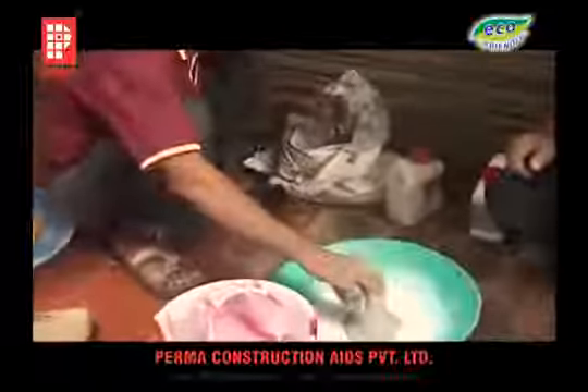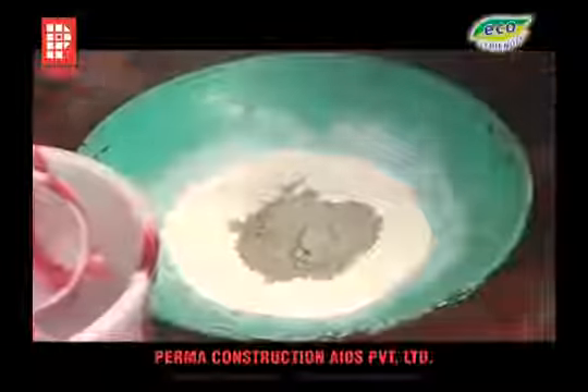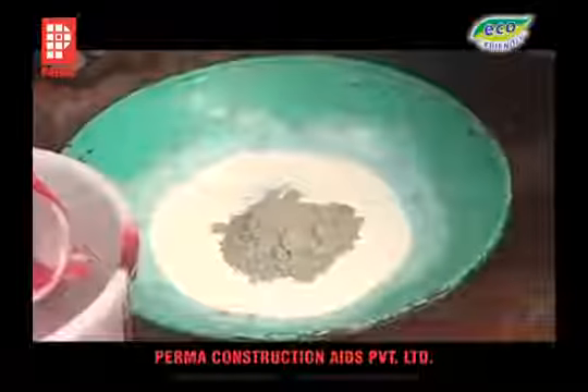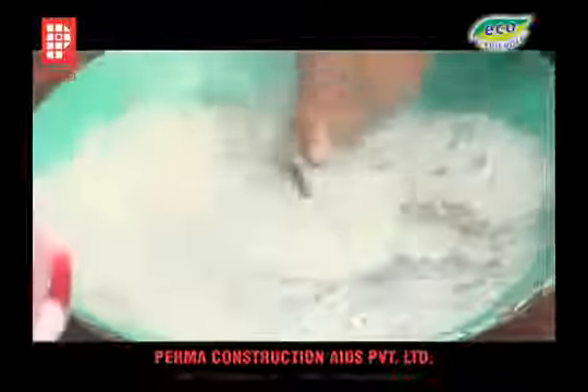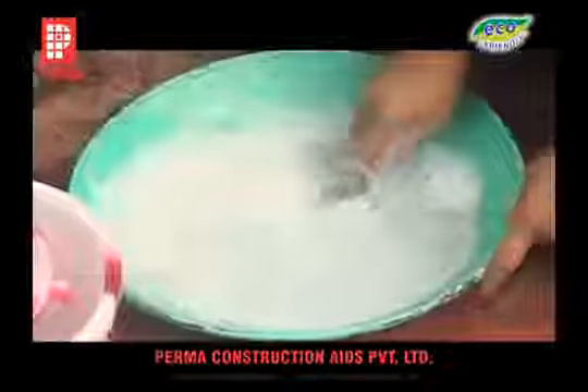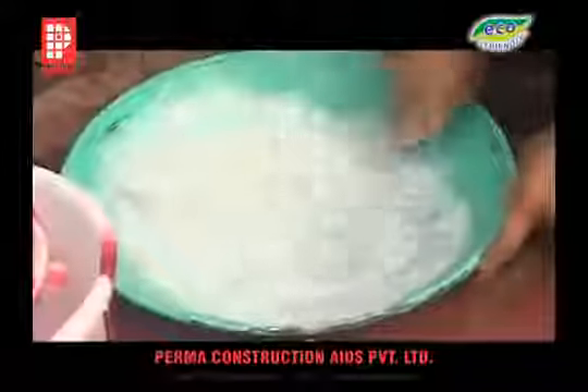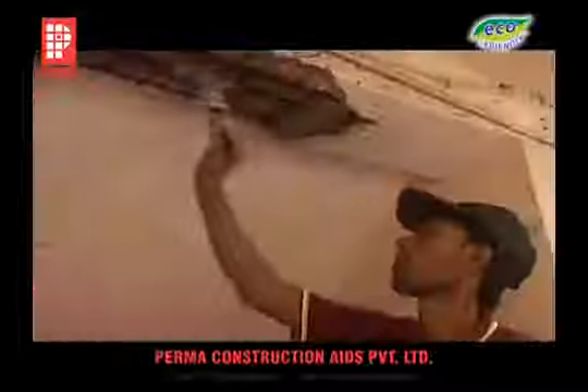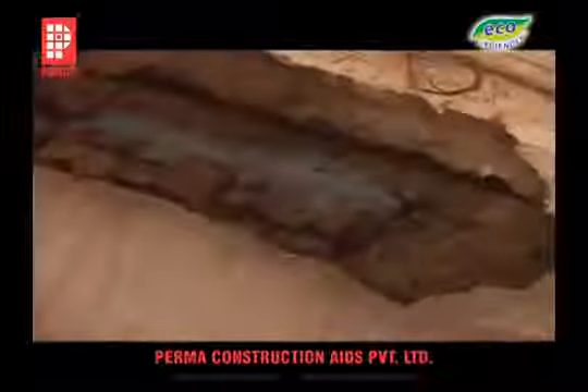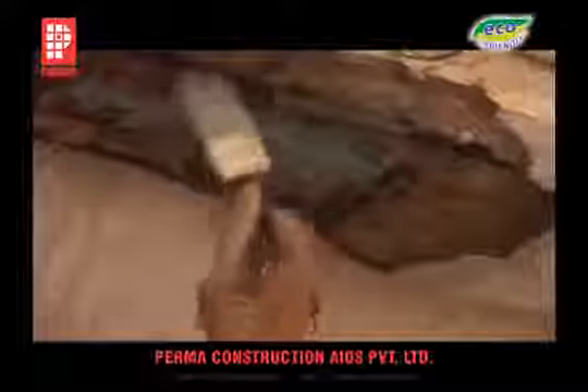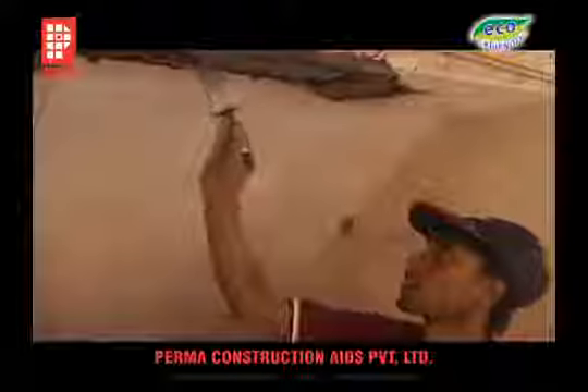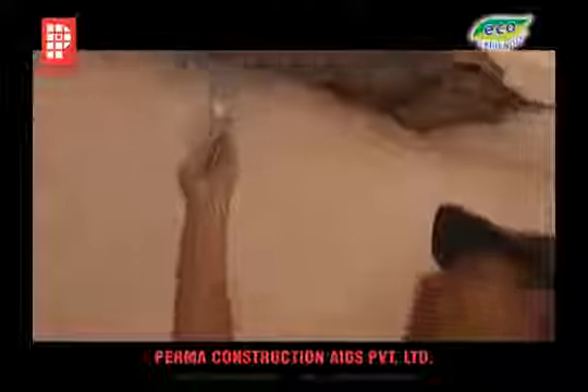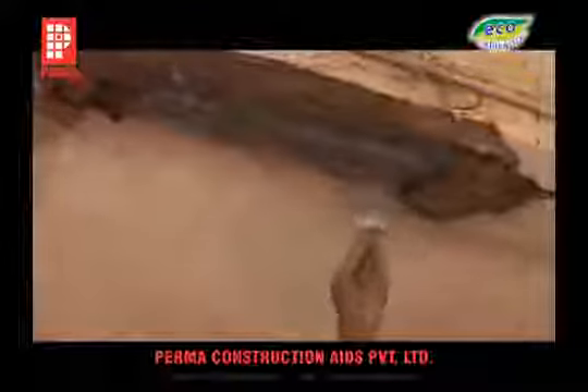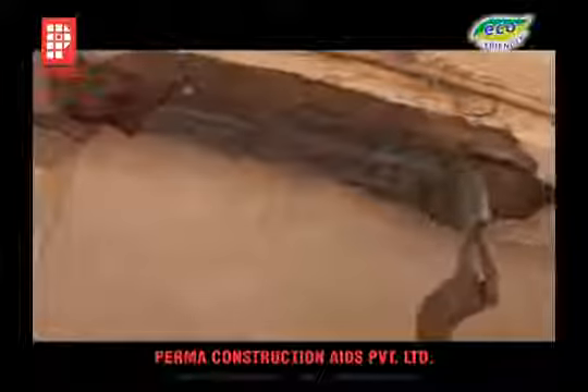Perma Bond SBR is mixed with cement in the proportion of 1:1 by volume. Here, 2 measures of SBR is mixed with 2 measures of cement. This slurry is brush applied on the cleaned, sound reinforcement and onto the added reinforcements, if any. This coat acts as a passivator coat, or a coating that prevents further corrosion of steel in future.